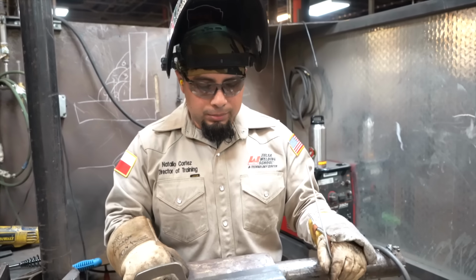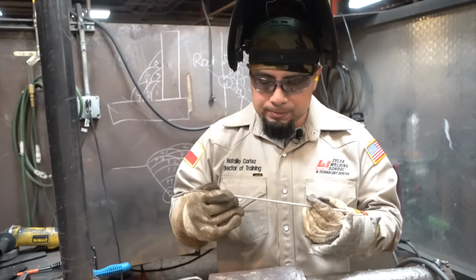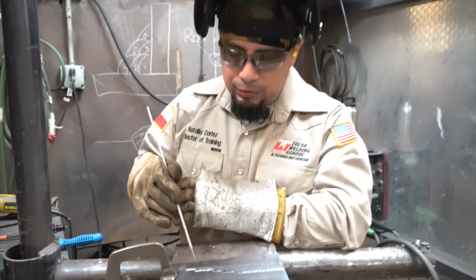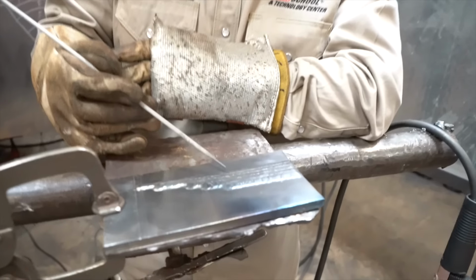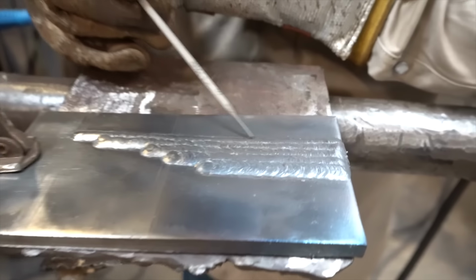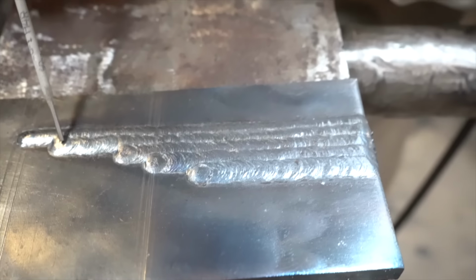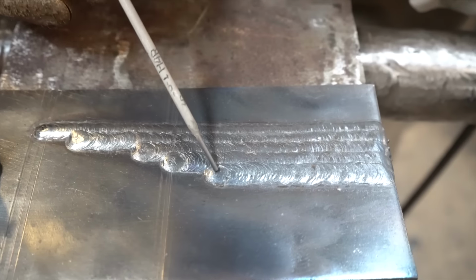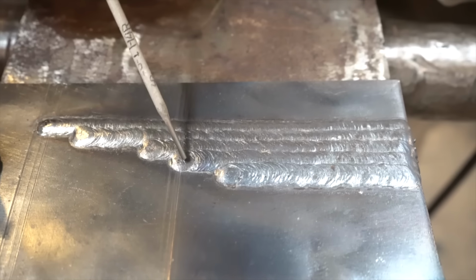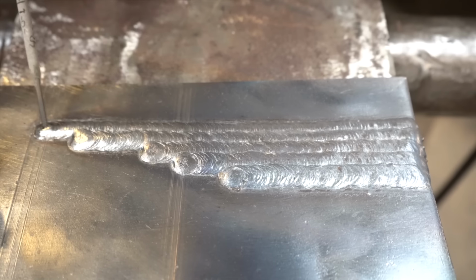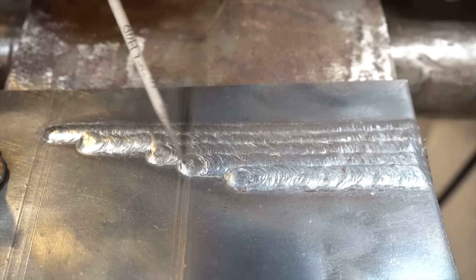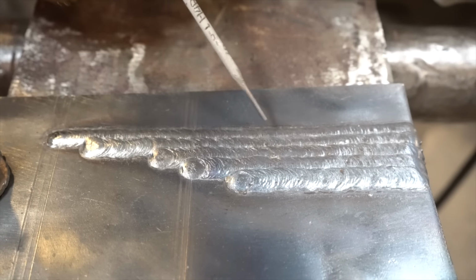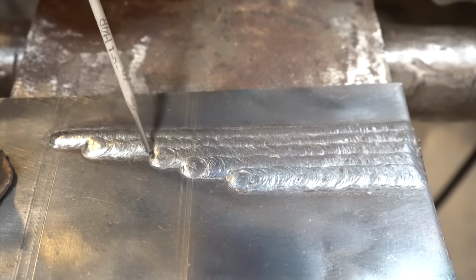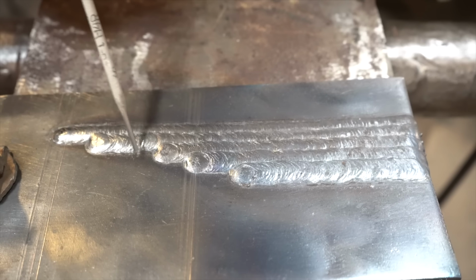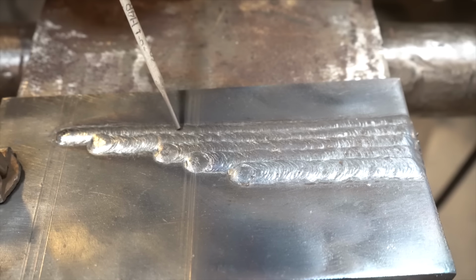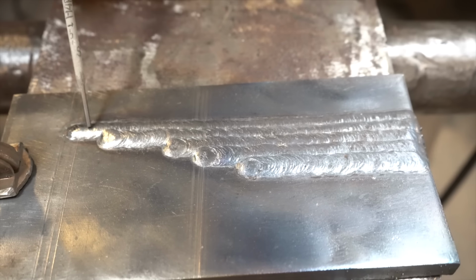Now that we've laid down about 5 overlapping welds, if you guys come in close, you can see the overlapping about 50% from that first weld to the second, third, fourth, and fifth. If you look at the end of each weld, each puddle, it's about the same width and the same length. On all the welds, I kept the tip on my electrode right on this top edge of every weld, except for this first weld, where we'll use a chalk line to keep it as straight as possible.